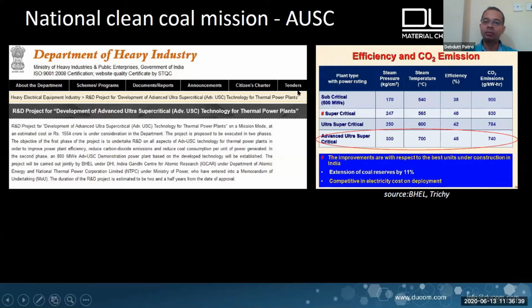In that context, what the Department of Heavy Industry is doing, as part of the National Clean Coal Mission, is to build advanced ultra supercritical power plants. Advanced ultra supercritical power plants, if you see on the right, operate under regimes which are very severe compared to traditional power plants. Steam temperatures can go as high as 700, and the pressures can be 300 bar. So the materials and infrastructure have to see a lot of aggressive conditions. The benefits are a significant improvement in efficiency, up to 45%, which is very good for traditional power plants, and a significant reduction in carbon dioxide emissions.